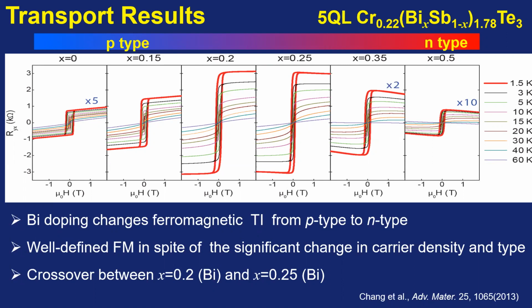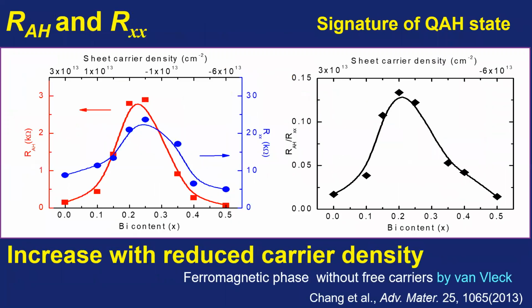But in this material, we can see that in both the P-doped regime and the N-doped regime, the ferromagnetism is always there. And we can see the anomalous Hall resistance between the P-type and N-doped is a little bit bigger. And we can see there is a crossover between the N-doped and P-doped between 0.2 and 0.25. Let's summarize the anomalous Hall resistance and the longitudinal resistance at zero magnetic field as a function of the bismuth content. We can see that the anomalous Hall resistance indeed shows a peak when the sample is in the insulating regime, and the longitudinal resistance also shows a peak in this regime.